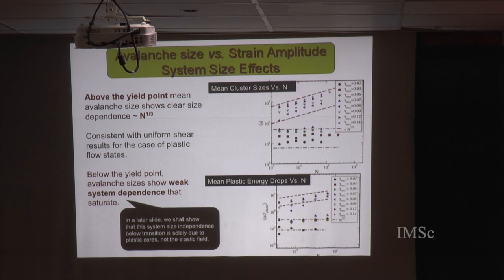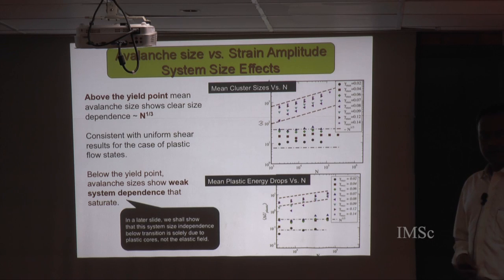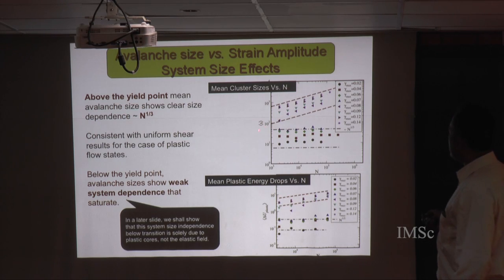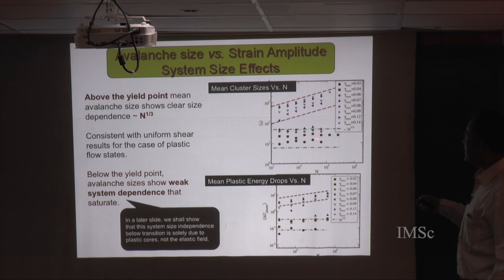what the system size effects are, and B, how that will help us identify where the yielding transition is, what I show here is the mean avalanche size in terms of cluster sizes and in terms of energy drops as a function of the system size, and each curve is a particular amplitude. So what you find is that for low amplitudes of shear deformation, the system size effects are basically negligible, right? So the mean avalanche size stays roughly constant.